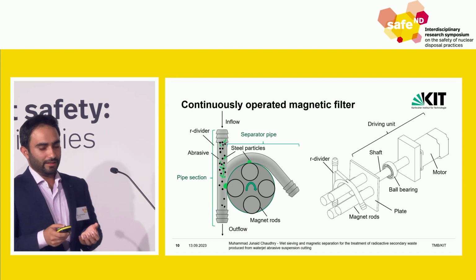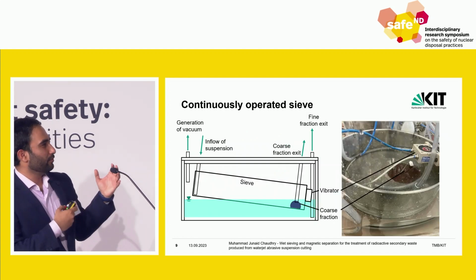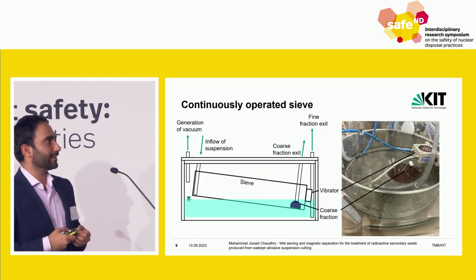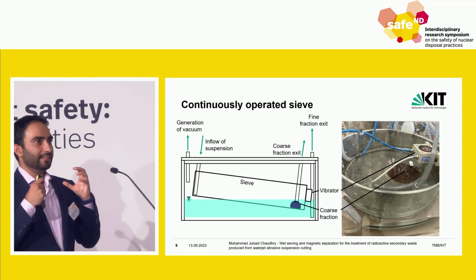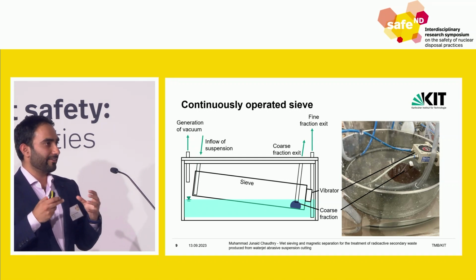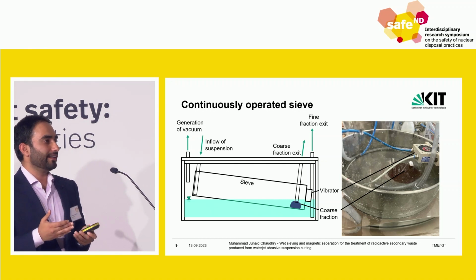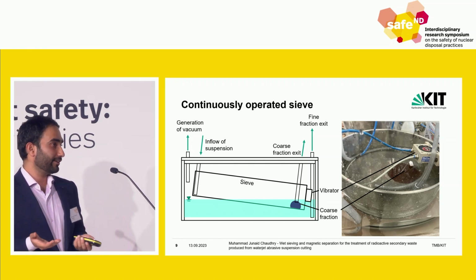So we have tested this continuous sieve, and what we call the sieve error is really low, lying between 3 to 4%.